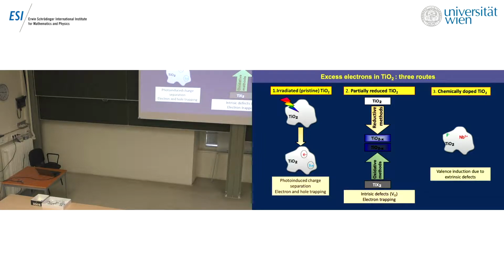And then there is this interesting method that is the valence alteration that I described before, that allows you to introduce one extra electron, in this case because you are talking about excess electron, using either a cation like niobium or an anion like fluorine. So I have to say that in all three cases, typical spectra of titanium 3+ are observed by EPR. So in some way, the excess electron interacts with titanium and produces titanium 3+ ions.